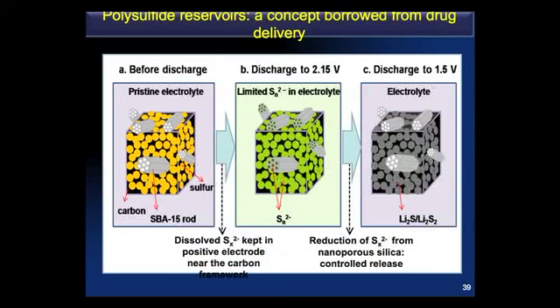So we incorporate these to the tune of 5 through 10 weight % in our carbon matrix. And on discharge, to the point where we have the maximum polysulfide concentration, these are absorbed into these little silica particles. But because this silica is insulating, they don't become reduced, they just simply diffuse out, such that at full discharge we now have the lithium sulfide, or Li2S2, incorporated in the carbon matrix. So they act as a little reservoir to contain the polysulfides just when we need them, and they are released in a controlled fashion on full reduction.